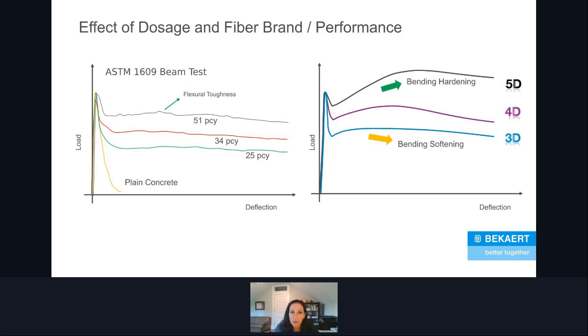Most notably, there's two key things to extract from this. One is you'd see the modulus of rupture, the cracking stress, does not change. So just like when you add welded wire mesh or rebar to concrete, it doesn't change the modulus of rupture. That's a characteristic of the concrete itself. So we don't expect that to change with the addition of steel fibers.